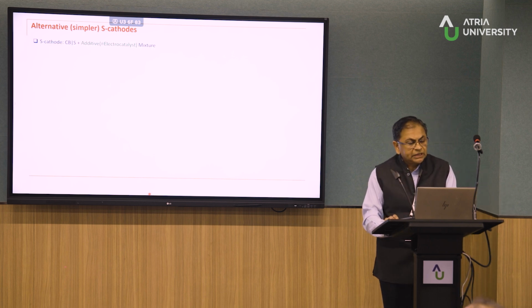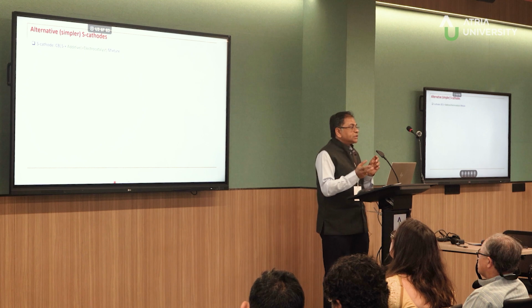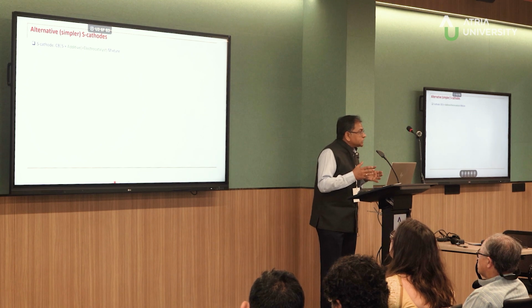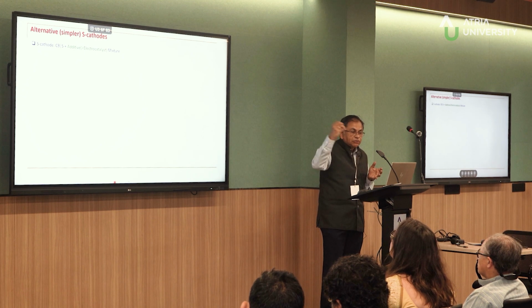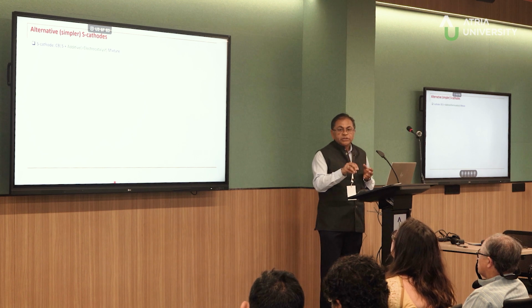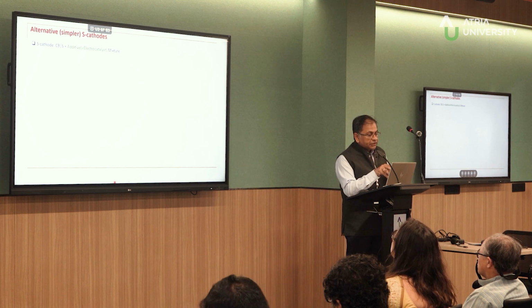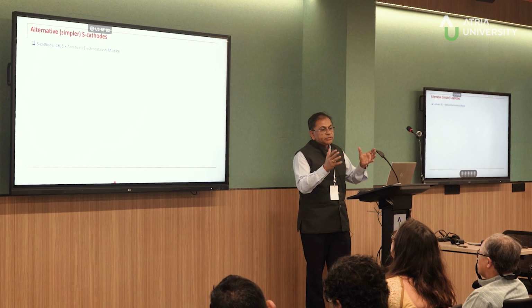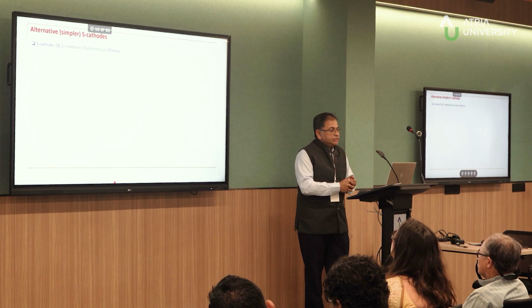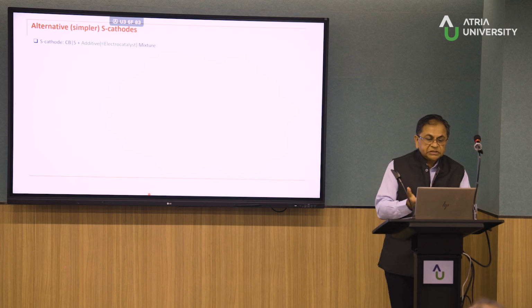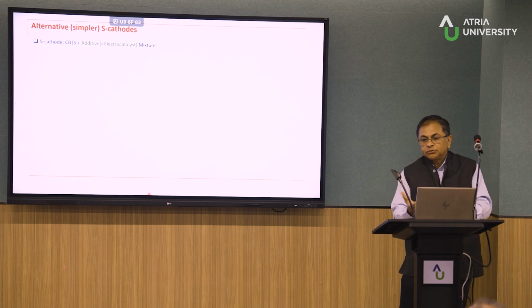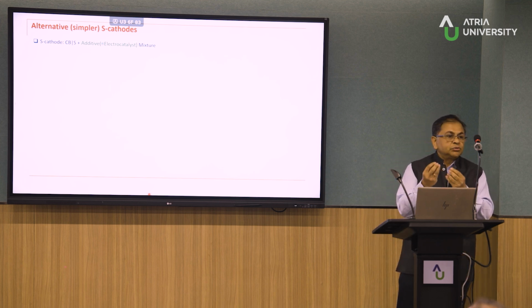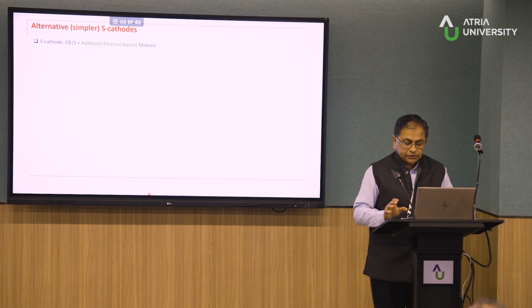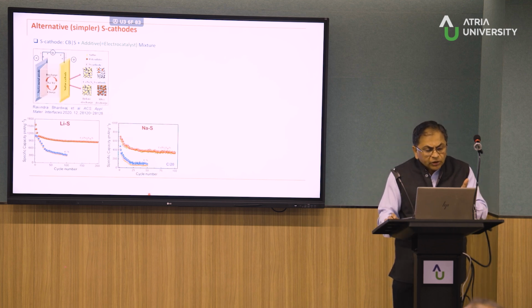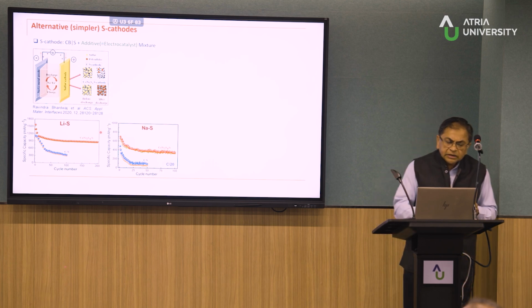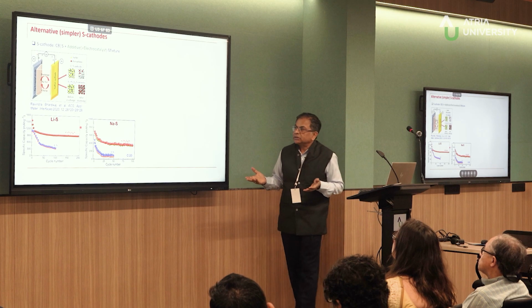So what we did was invoke something which Mustafa does, the concept of electrocatalyst, right, into the sulfur cathode. So you make your sulfur cathode much simpler. Just mix things like carbon black, very simple, like Ketjen black, mixed with a suitable amount of sulfur, and then you have a suitable amount of additive, which is an electrocatalyst. Okay, so this was one of our very early works. Again, it works extremely well, but it's only a paper, right?